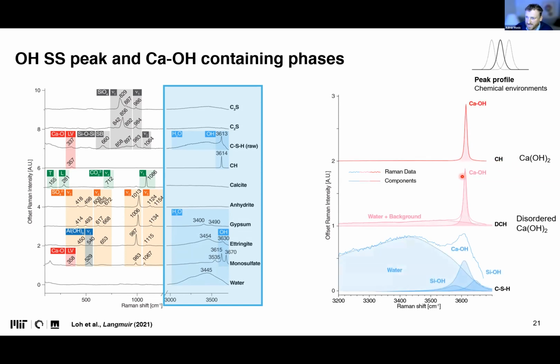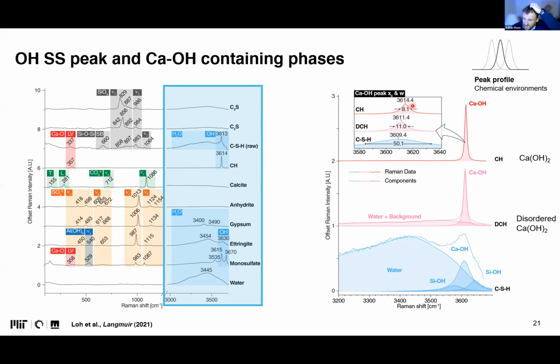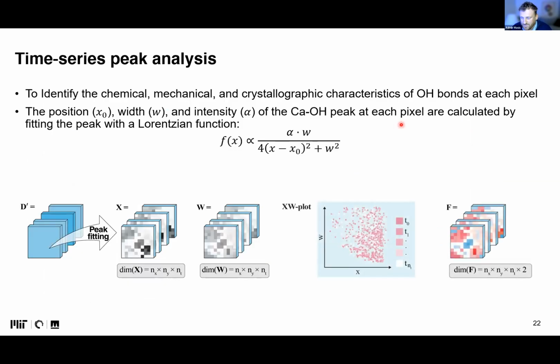we will notice by careful analysis of these peak positions and shapes that the OH peak associated with calcium hydroxide, which is typically very sharp when it crystallizes very nicely and is at about 3614, shifts in some of these stages and broadens. This tells us that the structure in this intermediate state is not yet crystalline but is somehow disordered, which is immediately picked up by this peak position and width. That then allows you to plot the position of the peak and the width. We can extract it through peak fitting of that specific peak.